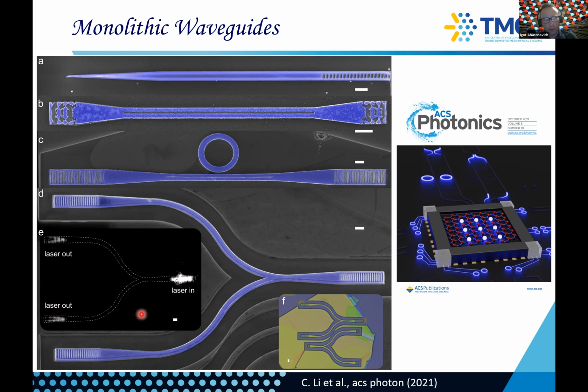We haven't done any fabrication directly with focused ion beam, which people sometimes do. So I don't really know about the damage distribution within hBN. We just don't have a good enough FIB in-house. And for etch chemistry, mostly SF6, a little bit of oxygen, argon, but we don't have any chlorine in-house yet. So it's a very standard, basically fluorine-based etching.